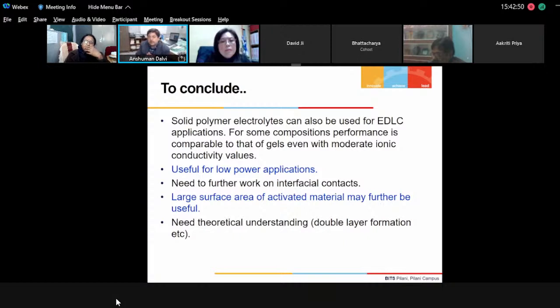That means what is the nature of the interface, what is the nature of the electric double layer which is forming at the interface, how the ions are able to diffuse in and out of those pores, that also has to be seen. And then finally, something interesting is definitely happening here. We are also working on large surface area activated carbon. Right now this is a moderate value of somewhere between 800 to 1000, but I'm sure that when we use large surface area and when we improve the interfacial contact, possibly this can be a very interesting new direction in